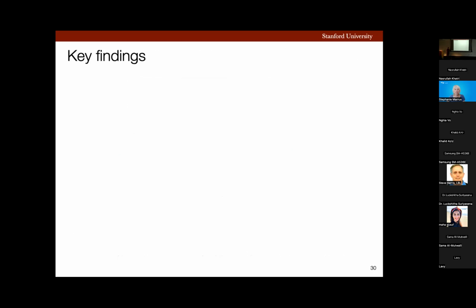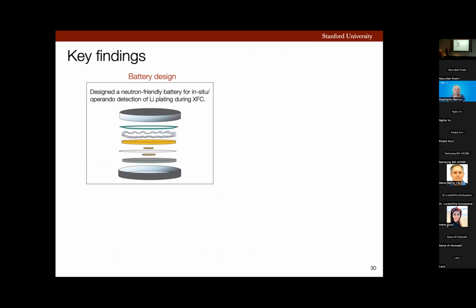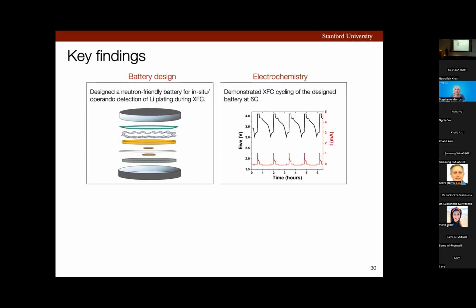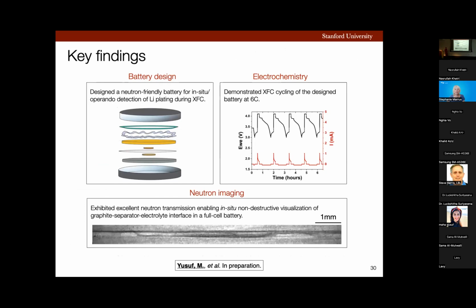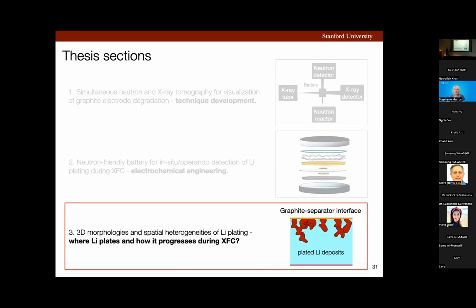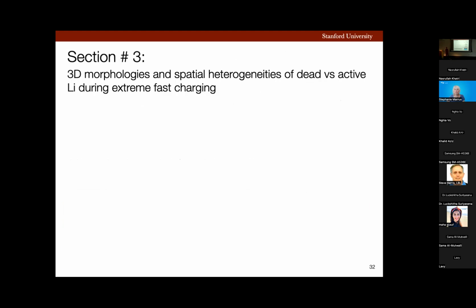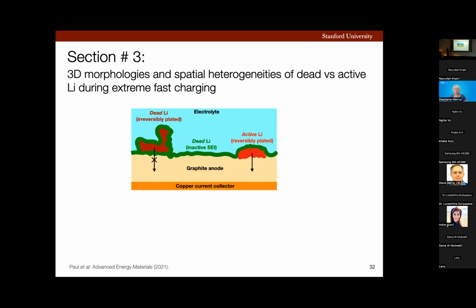Thus, to summarize, in this work, I developed a neutron-friendly battery for in situ or operando detection of lithium plating during fast charging. This battery is capable of fast charging at 6C, and the battery exhibited excellent neutron transmission, enabling in situ non-destructive visualization of this graphite separator interface in a full cell battery. Then I used my developed battery to investigate the fundamental questions about lithium plating during fast charging. Particularly, I investigated 3D morphological behavior and spatial heterogeneities of dead versus active lithium during fast charging.